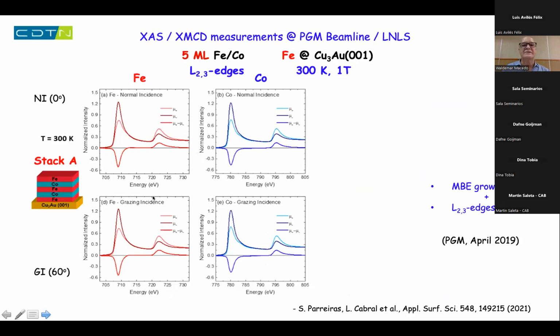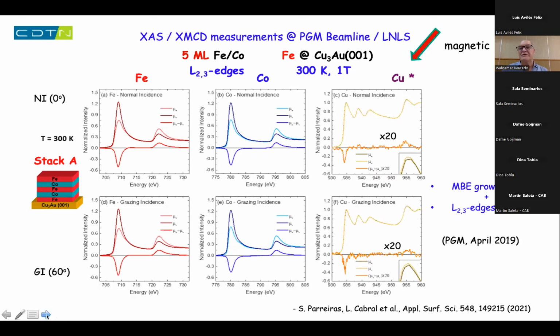We went to Campinas, and we wanted to see this same behavior, this reorientation depending on the top layer of the system, with the XMCD, but because of, let's say, contamination of the system, we have grown the samples by MBE, but we have to go through a not so clean system to get to the measurement chamber, and we didn't get this alternation of the spins in the system. But what you have seen there, of course, XMCD is element specific, but we don't have any depth resolution in these measurements. But what was interesting is that you have seen that copper, that means the non-magnetic substrate, gets magnetic. That you see an XMCD signal from the copper atoms.